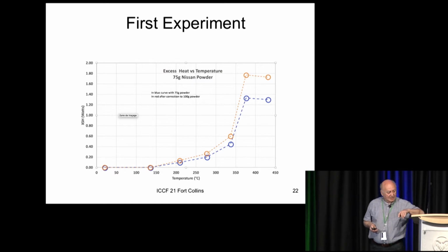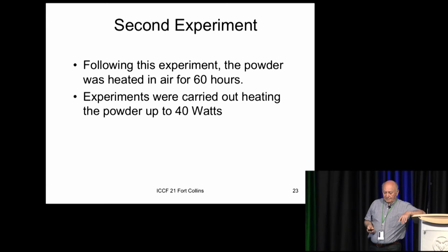So what I did, I removed the powder. You might ask, why didn't I go higher in temperature? Most of the time because the heating filament breaks. You know, that's a very casual problem we have. I removed the powder, heated it in air for 60 hours, and then started all over again. Okay. I'm using 40 watts maximum here.